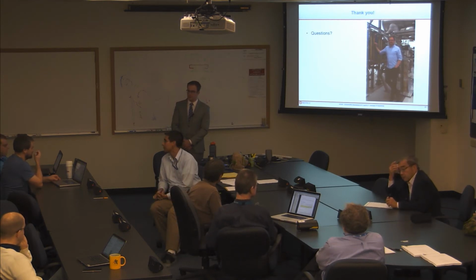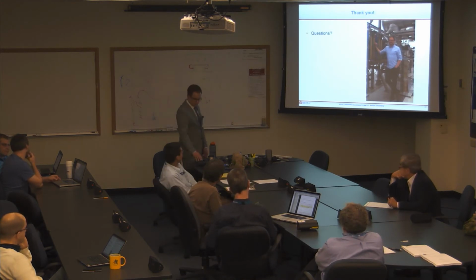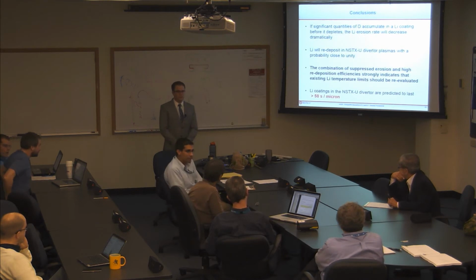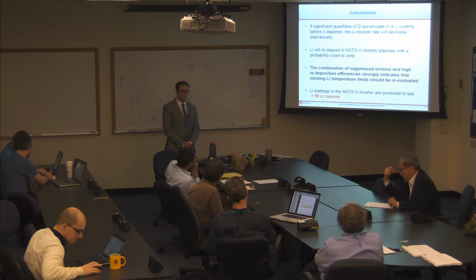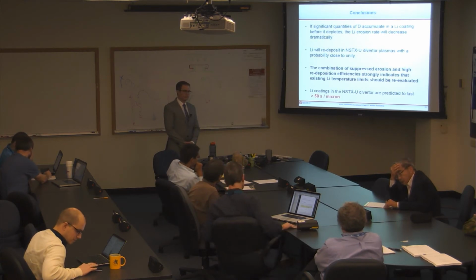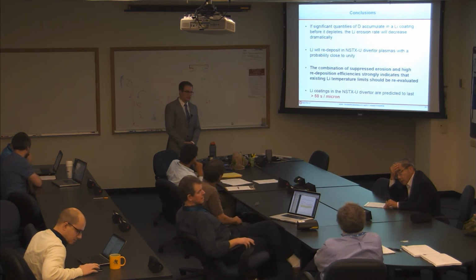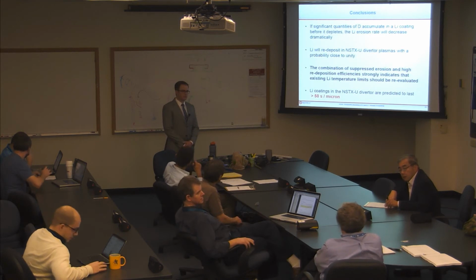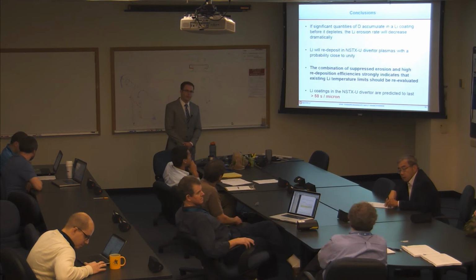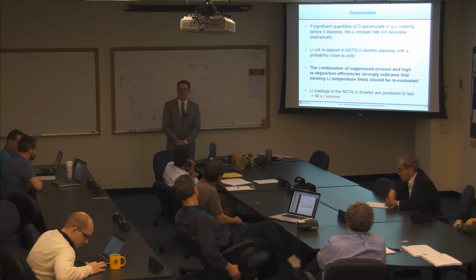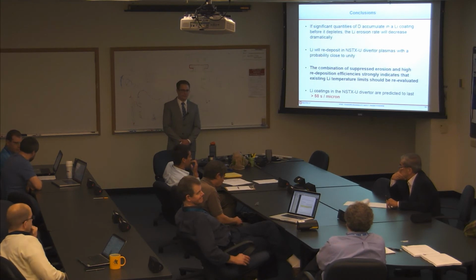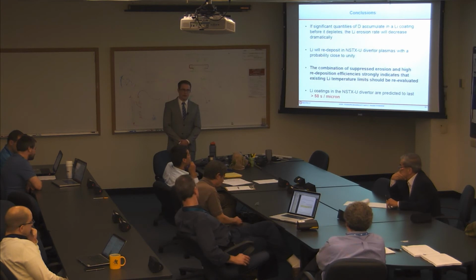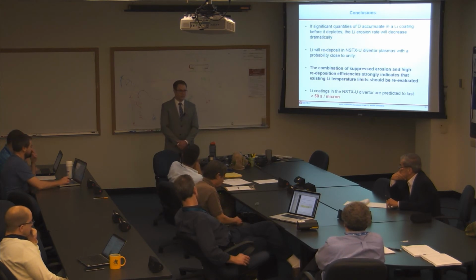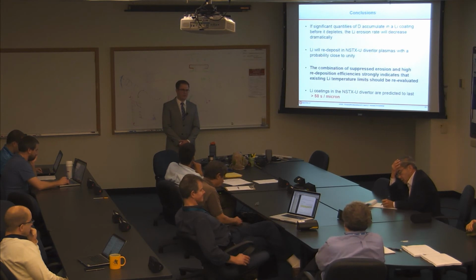I saw that. Yeah. So if you go back to your conclusions, the one in boldface there. The temperature limits were normally set by people just thinking about evaporation, I think. Yes. And you get lower than evaporation because the lithium deuteride has a higher surface binding energy, pardon me. I don't know if that's exactly the way to talk about it. That's chemistry, and you have the formation of lithium deuteride, and every compound and element has some vapor pressure curve as a function of temperature, right. And its curve is a lot lower. I'm not sure whether you can call that a surface binding energy effect, really. It's related, sure, yeah.